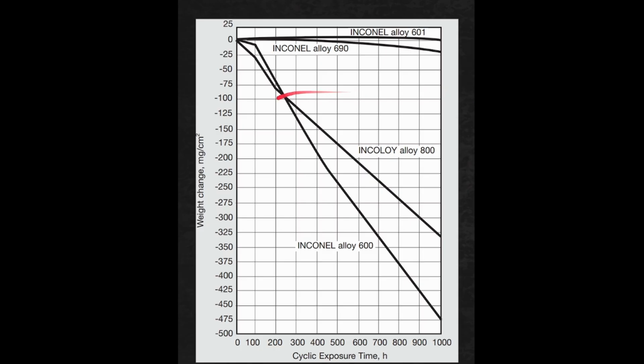Inconel alloy 690 sees much less decrease in weight change compared to Inconel alloy 600 under cyclic heating and cooling over the course of 1,000 hours. Here we can see that 600 does not hold up as well as alloy 690. That chromium by weight difference in Inconel alloy 690 made it much more resistant to the extreme temperature changes seen in a nuclear reactor.